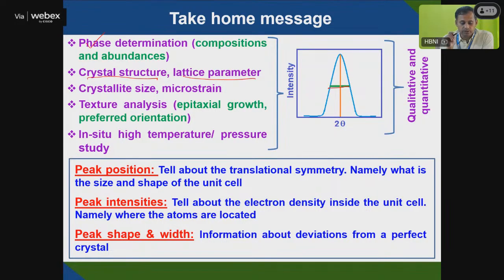So using those equations, lattice parameter A, then you can calculate crystallite size, microstrain, what is the strain built up due to nanoparticle, for example, and texture analysis, like whether it is an epitaxial growth. People will ask why only 200. If you take a thin film XRD, we will discuss next class, a thin film XRD, you will mostly get high orientation in one direction, then you will get a particular peak only. So texture analysis can be possible.